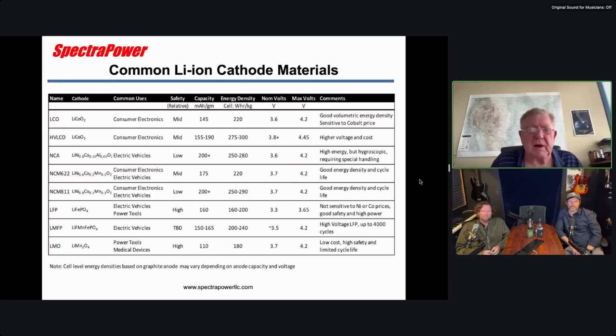But that kind of gives you, I think, a feel for the range of characteristics for the cathode. The cathode's really the determining factor in the cell energy density. There's usually a couple times more cathode than there is anode on graphite because it has lower capacity. So here we're talking 145 versus 372 for the graphite, right? So you need a lot more of this stuff to have the energy. Now you have to balance the capacity of the anode and the cathode, and usually you have a little bit of excess capacity in the anode, and that's because when you charge, you're moving the lithium ions over into the anode, and you don't want to have plating, so you want to have a little bit extra capacity over there. So does that make sense?